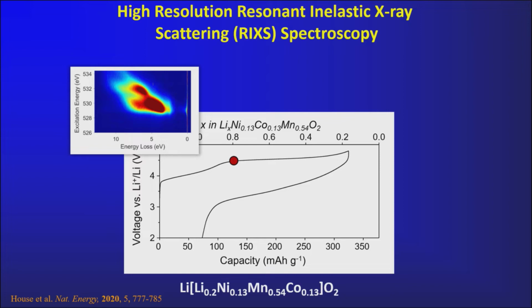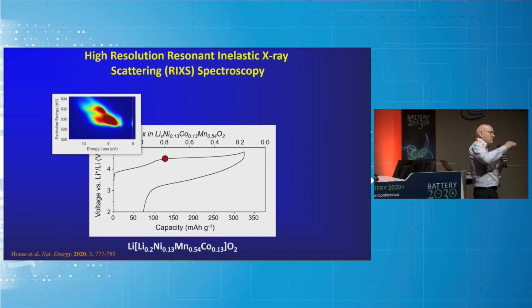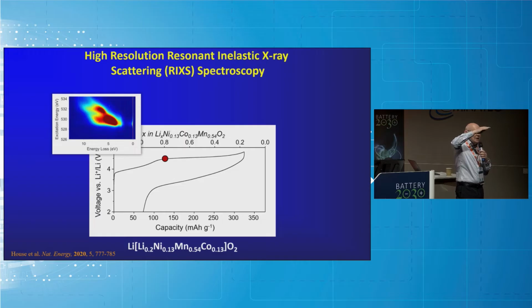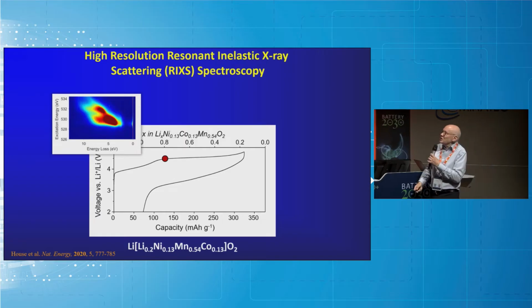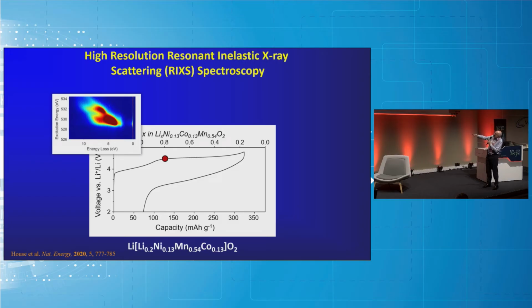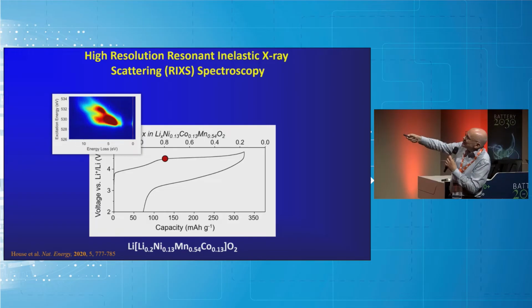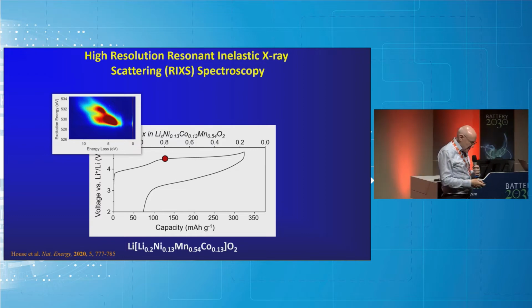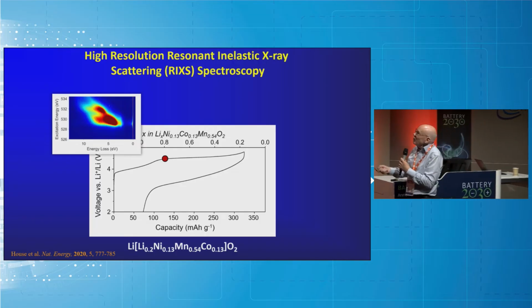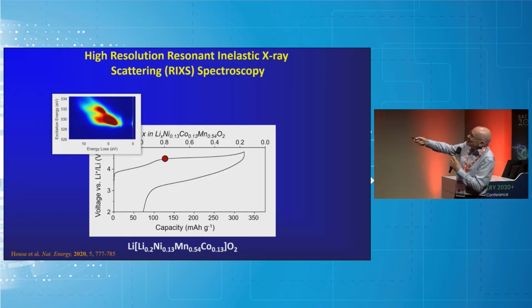Now, in RIXS spectroscopy, you excite at a series of different energies, or wavelengths, and for each one, you measure an emission spectrum. So you produce these 2D maps. On the y-axis here, we have the excitation energies in electron volts, and this is so-called energy loss. This is the set series of emission spectra. So for each energy, you get an emission spectrum, and 0 is when you're looking at the emission at the same energy as the excitation. So you create these maps. That's the map that you get from the RIXS measurement at the beginning of the plateau.